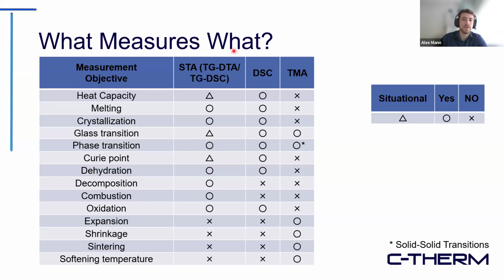Then next, we'll move on to the STA. Not as popular in the cold chain. This is just because the STA is really built for high temperatures. And if we're using our cold chain storage, we're normally at lower temperatures. So the STA, in certain situations, can do heat capacity, glass transition, Curie point. But what it excels at is melting, crystallization, phase changes, as well as things where there's mass loss. So decomposition, dehydration, combustion, oxidation.